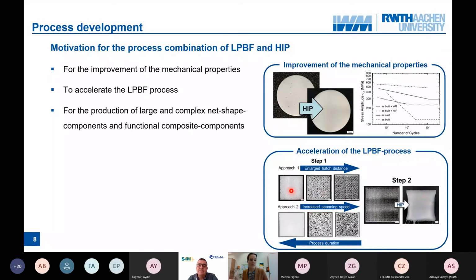And you can increase the porosity with two different approaches. The first is the enlargement of the hatch distance. That means the distance between the single laser lines during build-up. And the second approach is just a simple increase of the scanning speed. Both will result in more porosity, but both will also result in shorter building times. So you can save process time in the LPBF process. The only thing you need is a dense shell, because otherwise you cannot densify the samples in the HIP process.